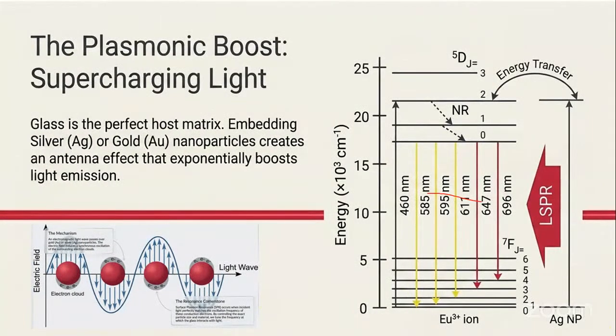So if I have to come up with the role of plasmonics in these rare earth based glasses, what I try to see is something called resonance energy transfer that occurs between the localized surface plasmon resonance and the emission wavelength of that particular material. If these two undergo energy transfer, they act like an antenna. These surface nanoparticles, gold or silver colloidal nanoparticles, play a very important role. They act as plasmonic antennas.